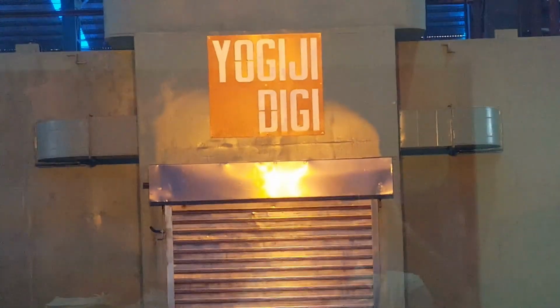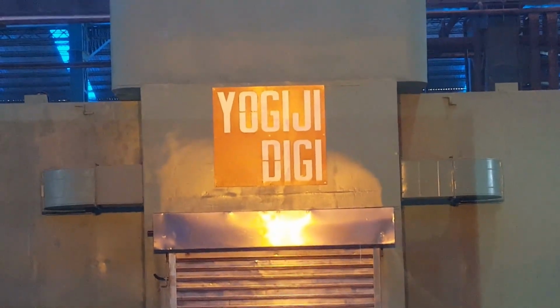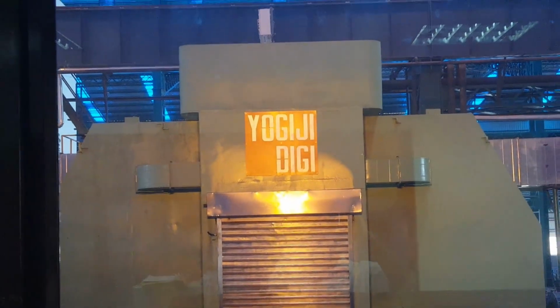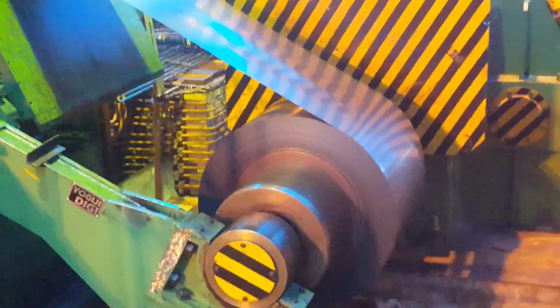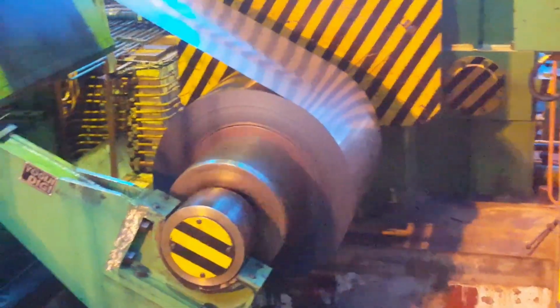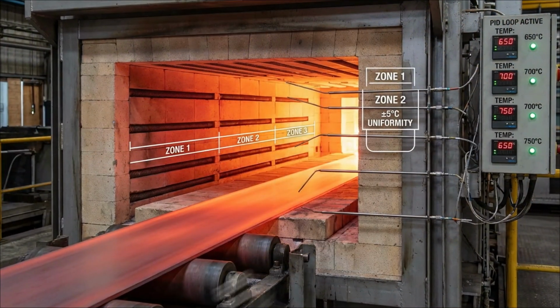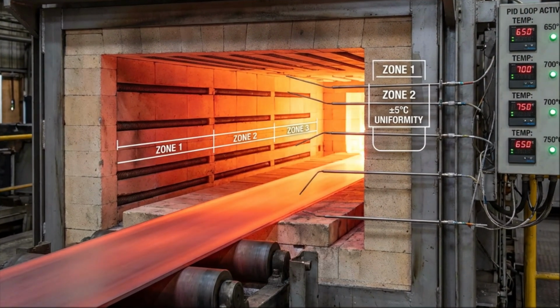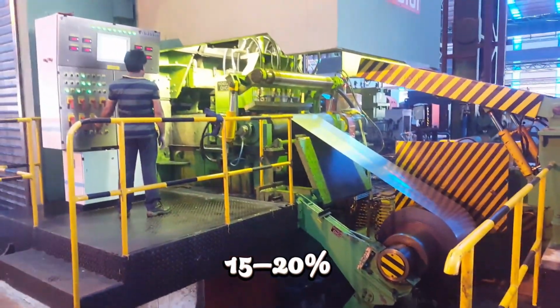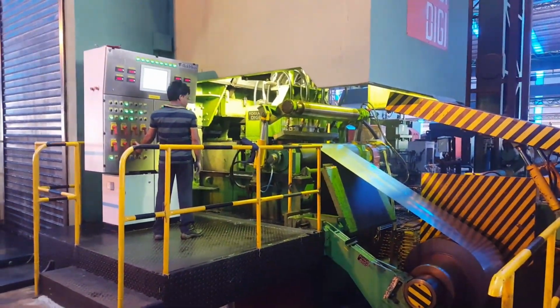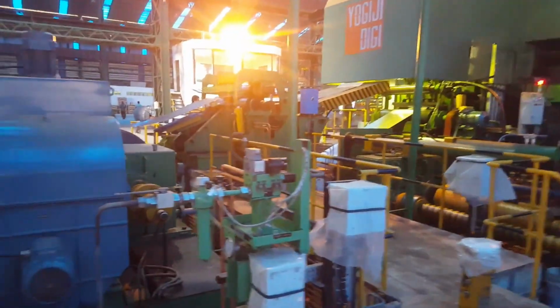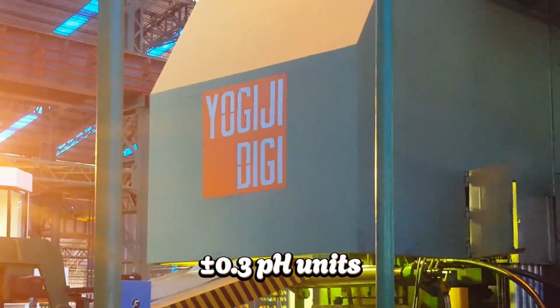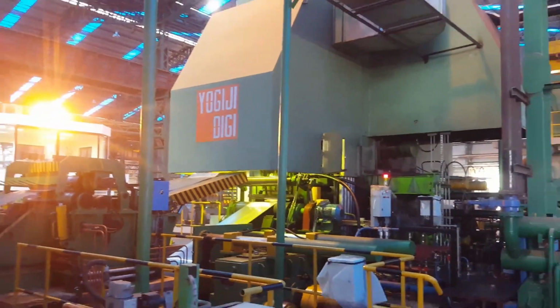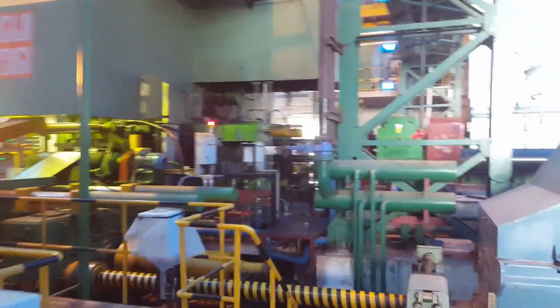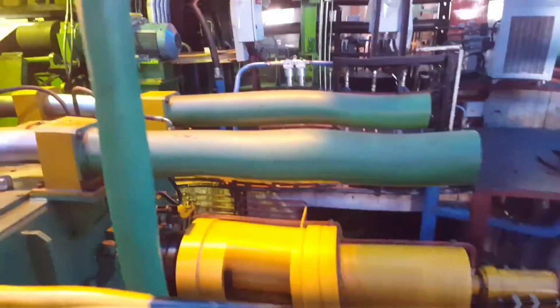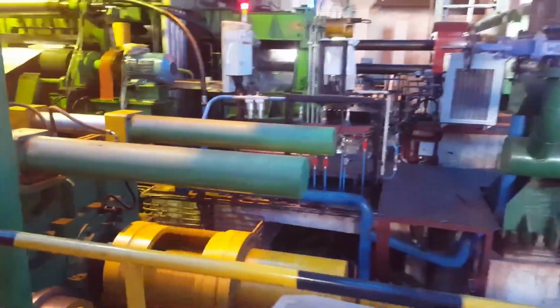Before steel can face 2,000-ton rolling loads, its surface must be flawless. Hot-rolled coils carry a millimeter-thick oxide layer. Pickling dissolves it at 80 to 90 degrees Celsius, using 15 to 20% hydrochloric or sulfuric acid. pH sensors hold the bath chemistry to plus or minus 0.3 pH units. If pH drifts beyond that window, micro-pitting forms, and the strip rips in the first stand.